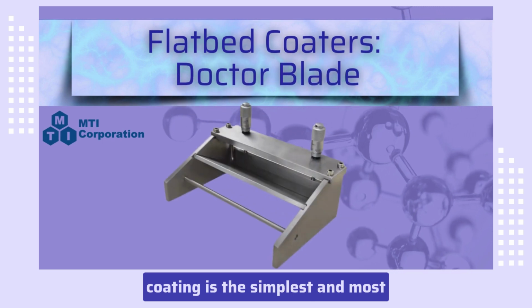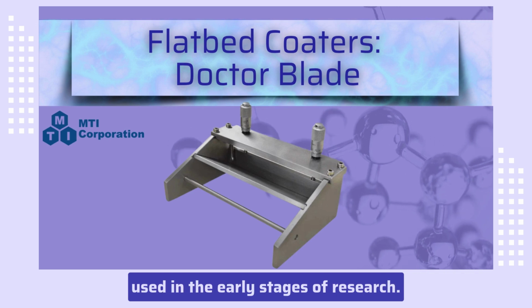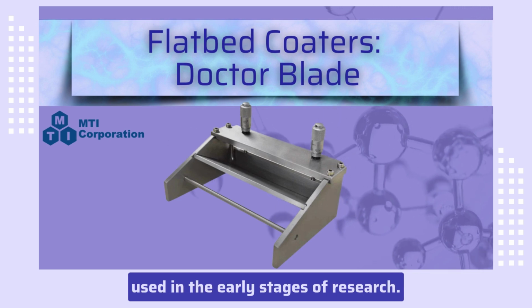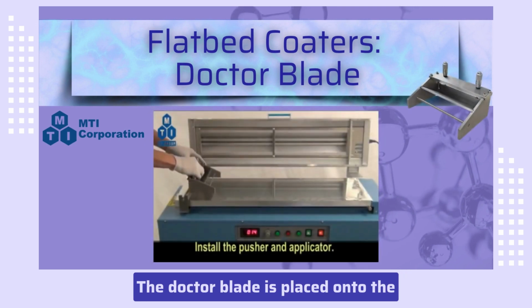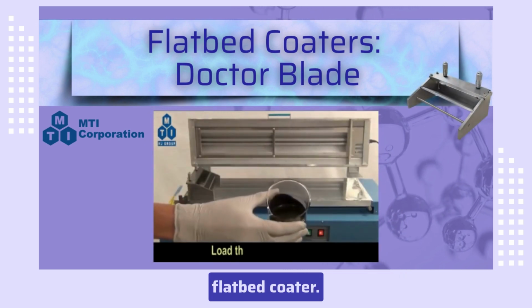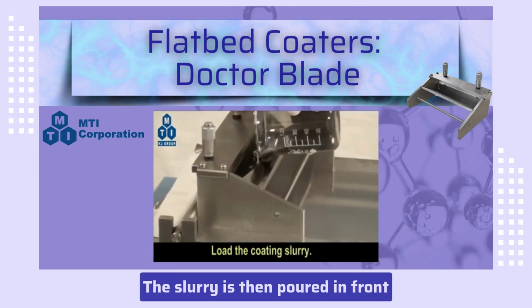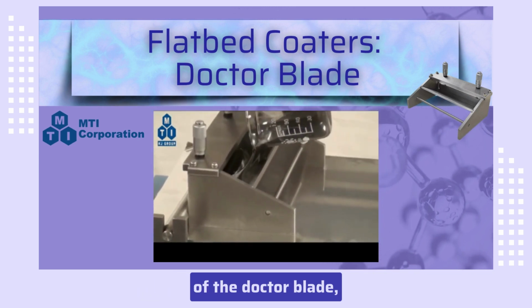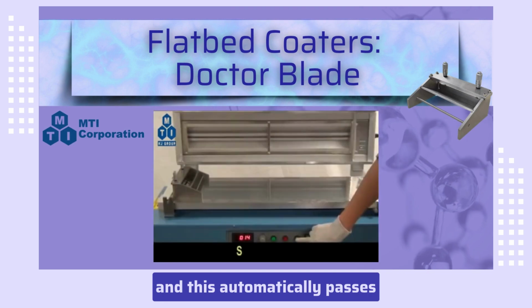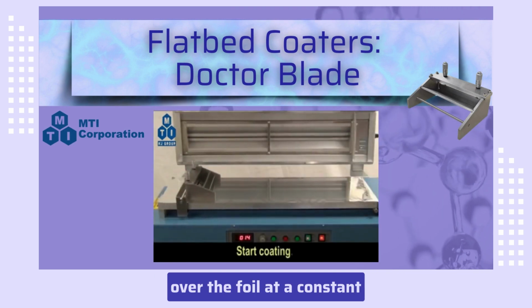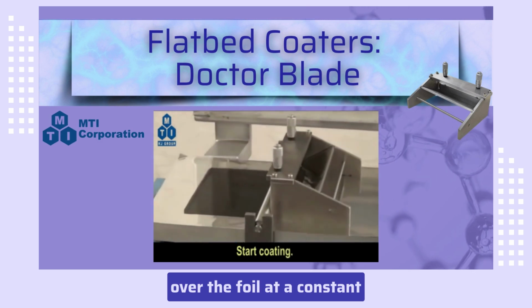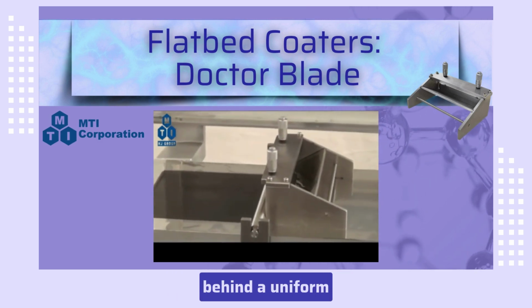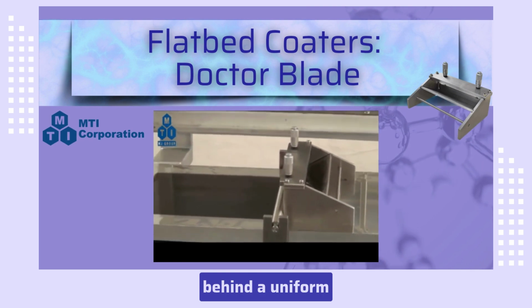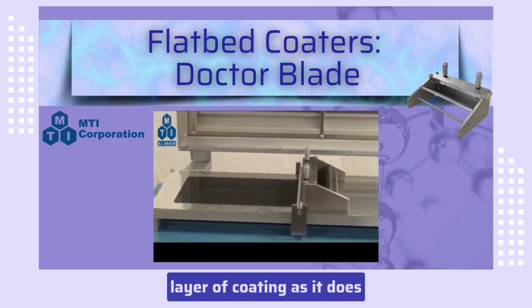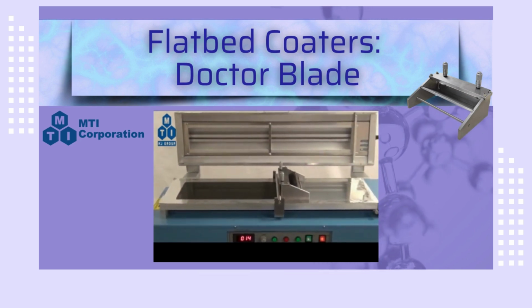Doctor blade coating is the simplest and most common method of coating used in the early stages of research. The doctor blade is placed onto the flatbed coater. The slurry is then poured in front of the doctor blade, and this automatically passes over the foil at a constant speed, leaving behind a uniform layer of coating as it does so.